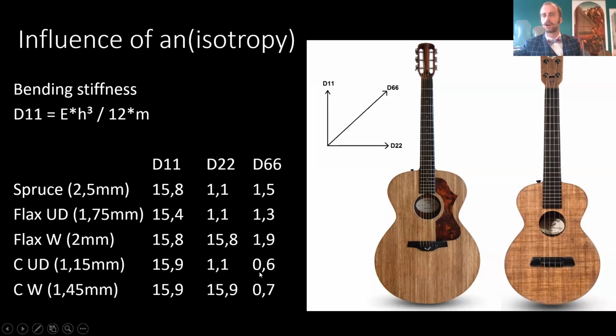So a carbon fiber plate is very easy to twist like this. So it is different from wood. Of course, you can try and manipulate them to be more alike, but that was not my intention, so I kept it like this. Of course, you can also use carbon woven, just like here in the flax fiber ukulele. And then you can also manipulate this, so then you have stiffness in 2 directions, but still the torsion is low. So depending on how you orientate the fibers, you get a different soundboard.